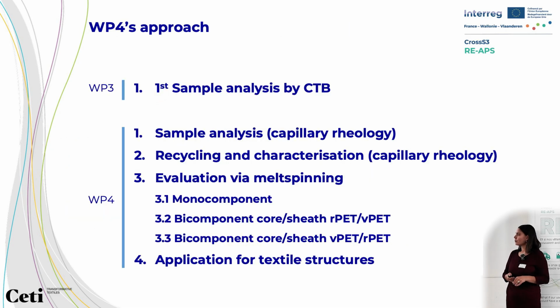The work package 4 approach can be separated in different steps. We have sample preparation in partnership with Centexbel. We then have the recycling and characterization, with specific measurements to see how the material behaves, not just by the IV measurement, but also under different shear rates. And then we have an evaluation by spinning. The way that we have decided at CETI is to first go through a monofilament to establish how the material behaves, and then enhance the properties of the recycled polyester by incorporating it into a bicomponent spinning, in the core-sheath formation. So first we do the recycled in the core and virgin in the sheath, and then we invert this configuration. And then the last step, the application for textile structure.